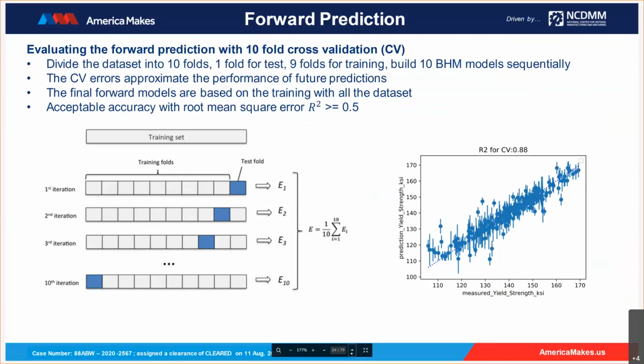In the right figure, the horizontal axis is the measurements of the yield strength. The vertical axis is the prediction from the 10 sets of small BHM models. And the identifiable confidence interval, basically the error bar, is also shown in that figure. Among these 200 data sets, you can see the predictions are almost aligned with the measurements, which is implied by the dashed 45-degree line. That means our prediction matches the measurements pretty well. The R square is as good as 0.88. R square equal to 1 means that our prediction exactly matches the measurements. And we're using 0.5 as a threshold value to identify acceptable accuracy. So all the quantities with R square lower than 0.5 from cross validation will be screened out for this model. The cross validation error is a smart way to infer the predictive performance at untested points for future use.